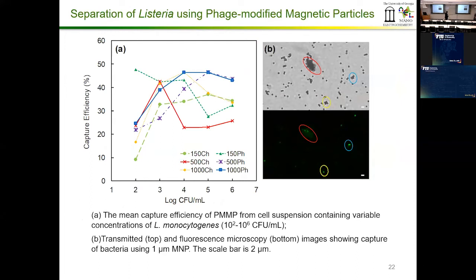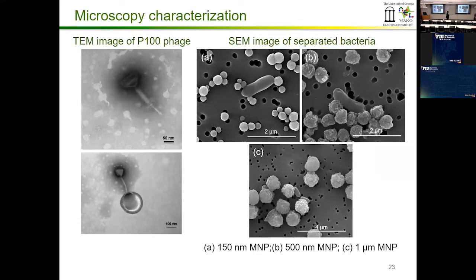We've done these experiments with different particle sizes of the magnetic particles, and these are some results. You can see there's a huge variation in the capture efficiency, so it's not really dependent on the particle size when you're dealing with microparticles. With nanoparticles, we haven't done the experiment because it's hard to obtain nanoparticles of iron oxide commercially. But what I was trying to say is we were able to capture anywhere from 40 to 50% of the bacteria at any time, which is better than none if you want to go through the enrichment route.